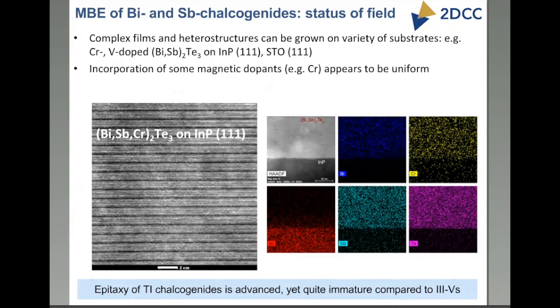Nonetheless, if you do high-resolution TEM images of some of these doped samples, you find that when you dope bismuth antimony telluride with something like chromium, it seems to go in a fairly uniform way. We can't completely rule out nanoscale segregation, but it looks pretty good. So this is again giving you a sense that we can grow samples here. We can characterize these samples. All the characterization that you've seen, X-ray diffraction, TEM, has been done here at Penn State. And when there are sample requests, we can certainly make sure that these samples are carefully characterized.